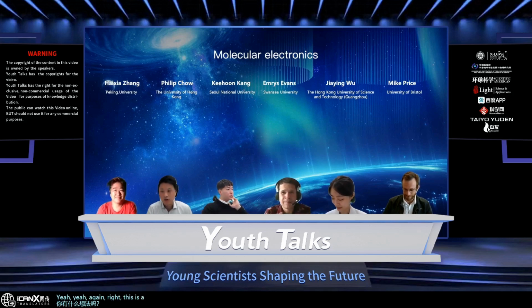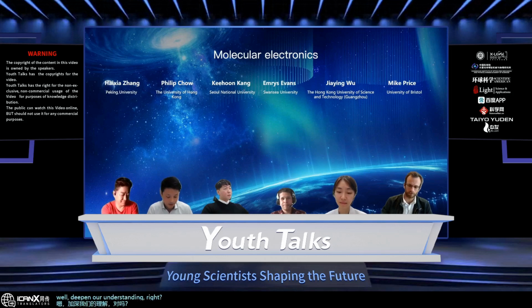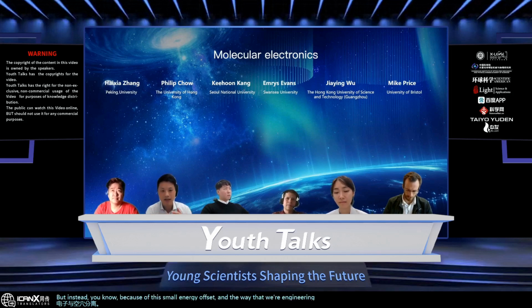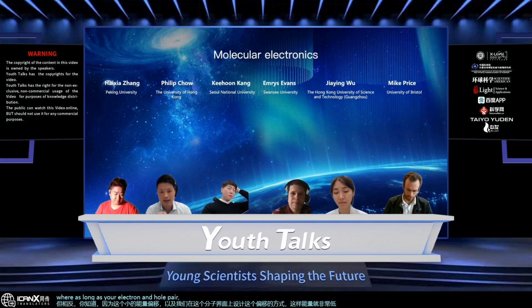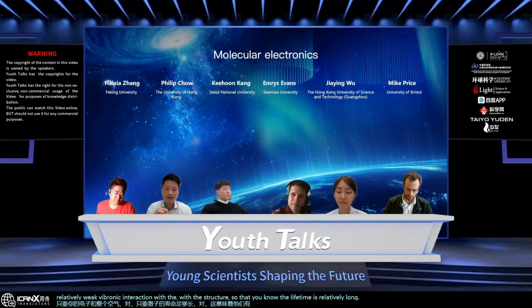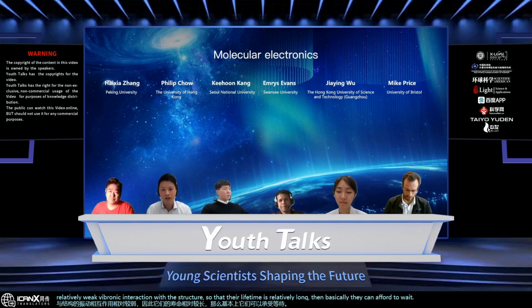Yeah. Again, this is a really good question, and for sure there are still a lot of things we need to do to deepen our understanding. From what I personally believe, in all these systems with very small offsets, the energy offset doesn't really play a major role in helping the electron separate from the hole. Instead, because of this small energy offset and the way we're engineering this molecular interface, there are very low amounts of energetic disorder. As long as the electron-hole pair lives long enough, meaning they have relatively weak vibronic interaction with the structure so that the lifetime is relatively long,